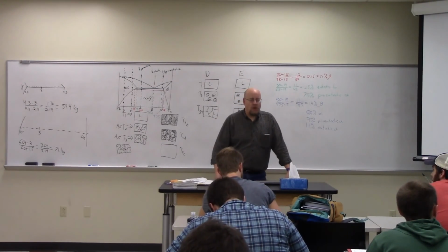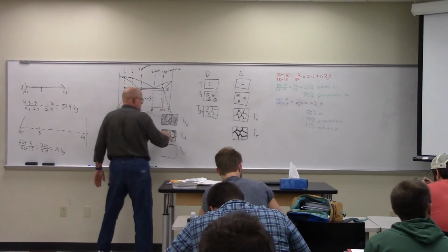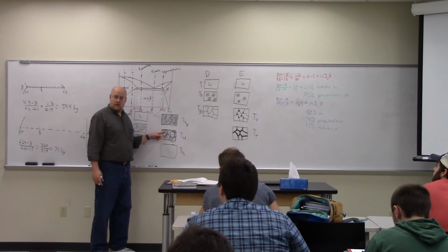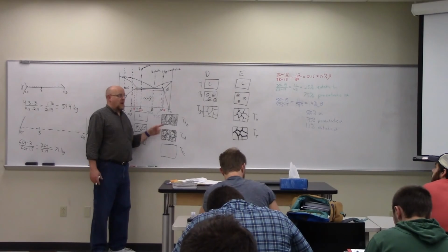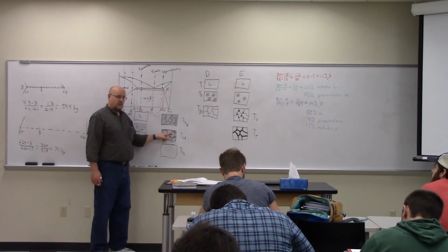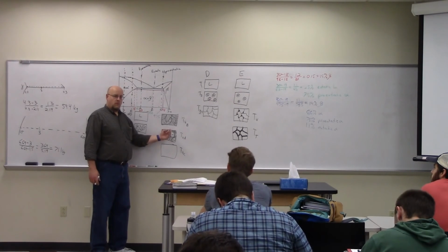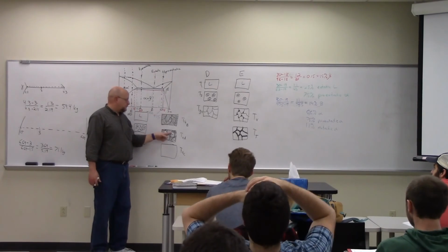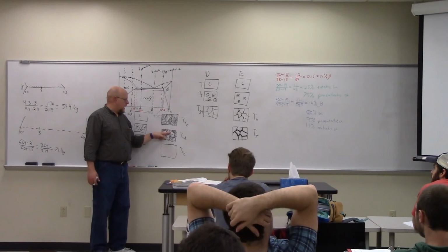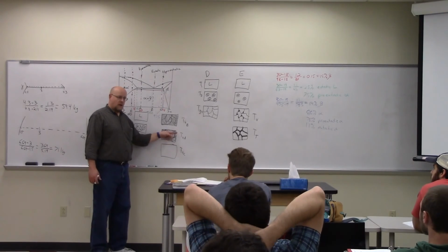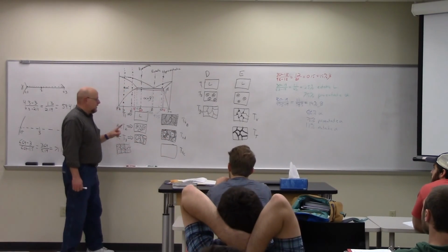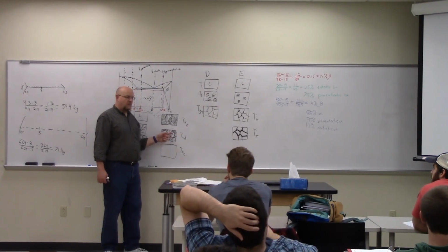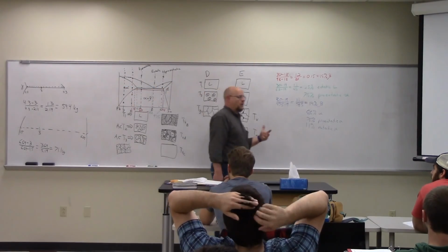And what will really happen is, you form something that looks like this, right? Proeutectic austenite, so it would be gamma instead of alpha, and then the eutectic material in between. As we continue to go down, some of this stuff will sort of dissolve away, and the amount of cementite will increase, so you'll get diffusion of carbon along the grain boundaries, and you'll form cementite along the grain boundaries like this. So some of that proeutectic alpha will be eaten away.